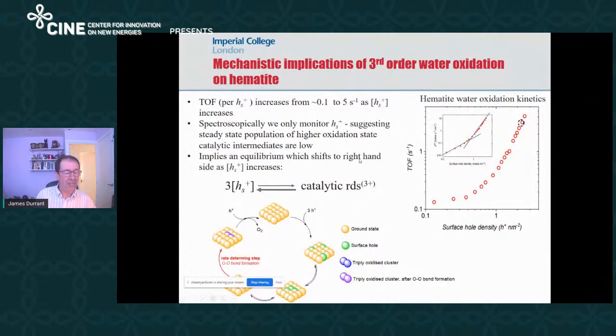When we come back to the water oxidation on hematite, which maybe is the most classic system we've studied, then what we observed, as we said, was that the kinetics, so if you plot it now as turnover frequency versus hole density, increase as we increase the hole density from about 0.1 to 5 per second. We should note these hole densities are large, so we're talking about 1 hole per square nanometer as being the point at which you change mechanism of reaction.